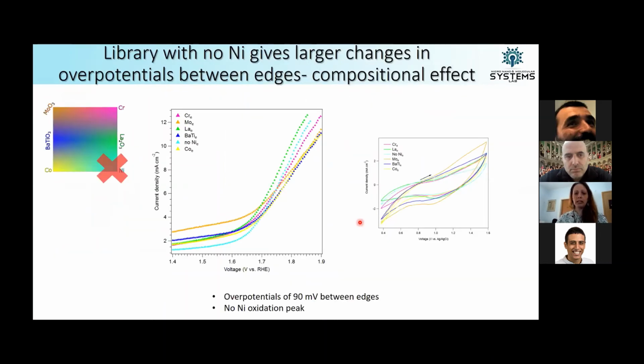We then also went on to synthesize a library that didn't contain any nickel at all, and immediately we see much larger variations of 90 millivolts between the different edges, which is what we expected to see. So this is more of a compositional effect versus what we saw before, which is more of a nanostructure effect.